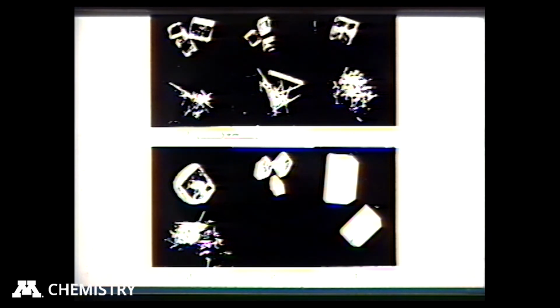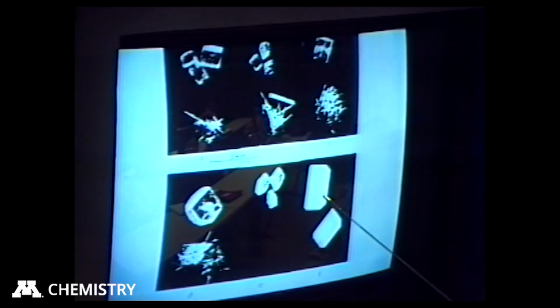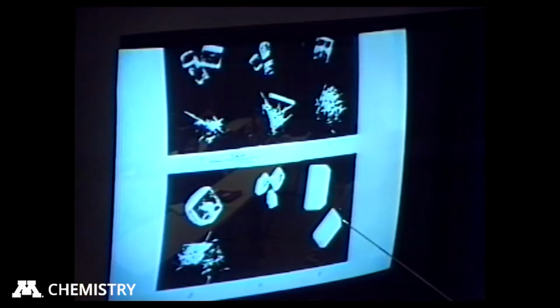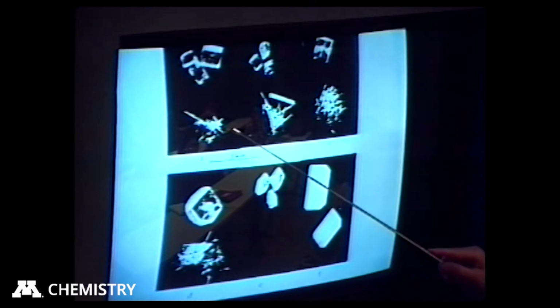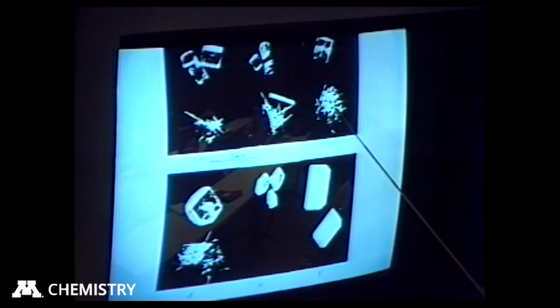But I'm going to show you several different crystals here. These two crystals are just plain triphenylphosphine oxide. It grows in 3 polymorphic forms, and I'm just showing you one of them here. And the more stable form are great big huge crystals. So triphenylphosphine oxide really likes to grow nice big crystals. If you take the triphenylphosphine oxide and grow crystals of other organic molecules where the organic molecules grow crystals that look like this, the co-crystals look like this.